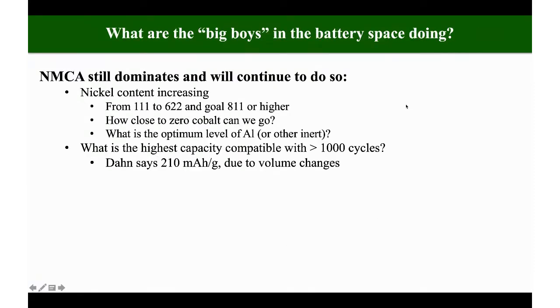So if you look in all the big companies in the battery space, this includes all the Asian ones, Tesla in this country, the nickel content in the NMCA is increasing. A few years ago, it was the equal amounts of nickel, cobalt, manganese. It's gone now to 60% nickel. And this is mostly because it's the cobalt price driving the cost of the cathode. So the fewer amount of cobalt there, they can cut the cost substantially. Clearly, there are also other child labor issues that are driving this. And the goal is to go to 80% nickel or higher.